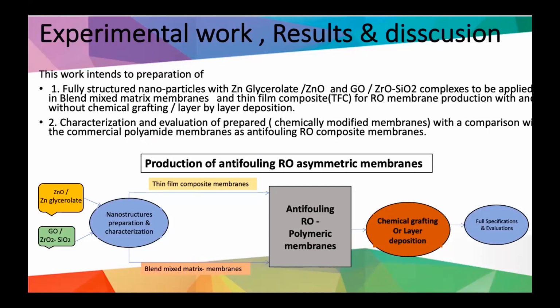In our experimental work, we are devoted to the presence of zinc glycerolate, and graphene oxide coupled with zirconium dioxide and silicon dioxide, and how to get these nanostructures embedded in the membrane preparation, embedded in the thin film composite, and also in the other layer by layer deposition, because we believe that the thin film composite alone will not be able to face all the aforementioned problems. So we need some mixed, some deposited layers by the layer by layer technique to get rid of some of these problems and get the membranes to be better and better.